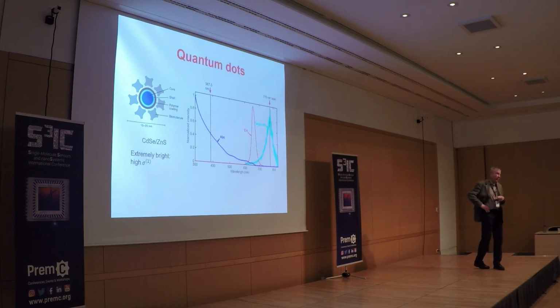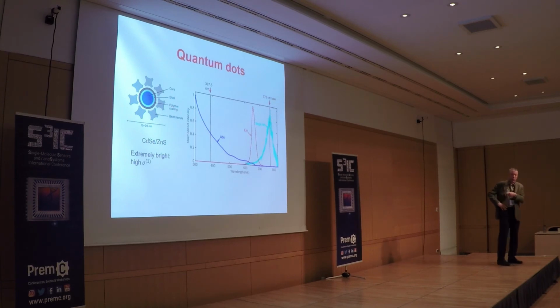And secondly, of course, I do not guarantee that there is no quenching. There may be already a lot of quenching. And actually, in the calculation, the quenching is also included. And the distance has been taken reasonably to correspond to the structure. So you can calculate it. The quenching may be there, but that doesn't prevent you from seeing the emission. Some degree of quenching is completely tolerable as long as you have enough photons coming out, right? So definitely there should be some quenching. I cannot tell you from memory how much it was, but it's definitely more than 10 or 20%. But definitely not 90% or more.